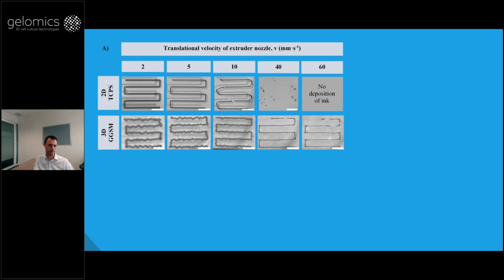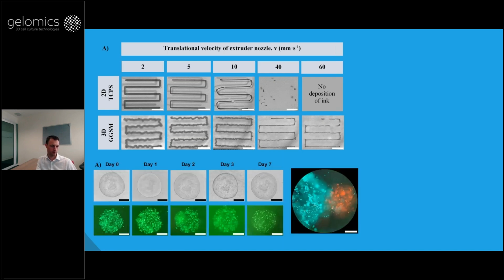So here, when printing into it, we could attain much higher printing speeds than on a surface, up to 60 millimeters per second. And interestingly as well, if you slow down on a surface, the gel will just spread and make a wider filament. But here it actually starts meandering a bit in the suspension media. So you can create this tortuosity, which might be interesting for some specific models, if you wanted to model a gut or something else. So we could also print with droplet printing, with the cells in droplets, and kept them alive for over a week, and also print different cell populations close to each other to make multicellular constructs in the suspension media.